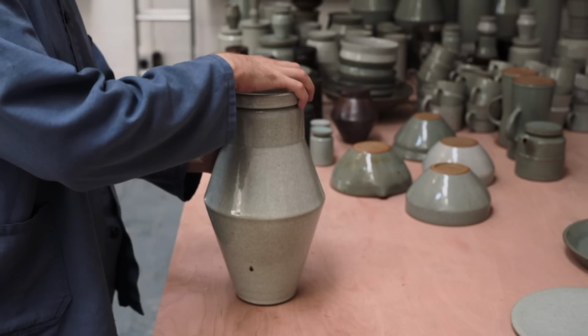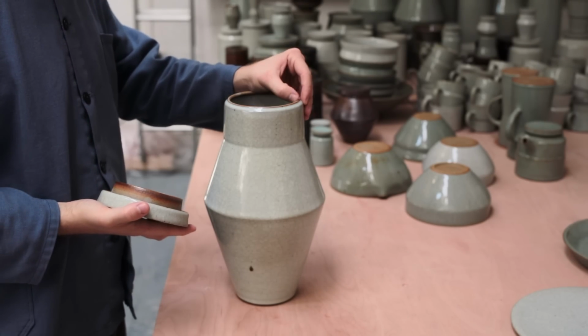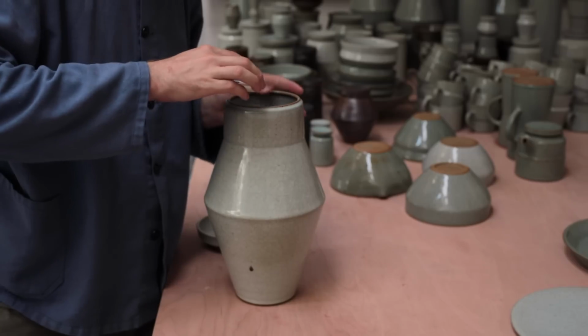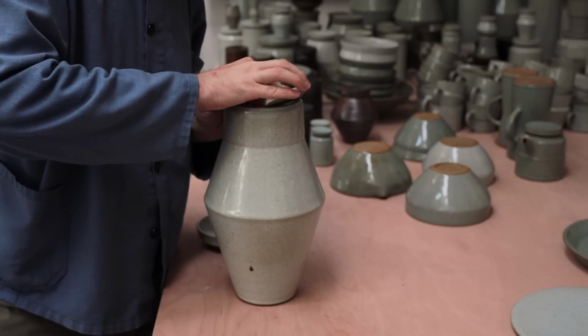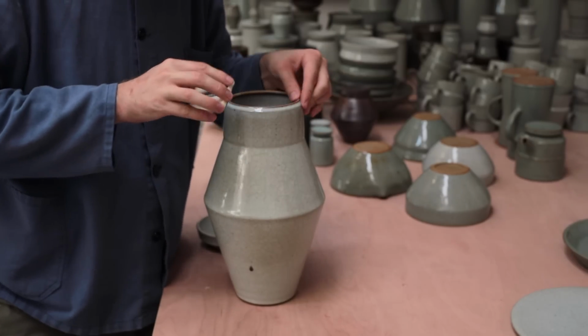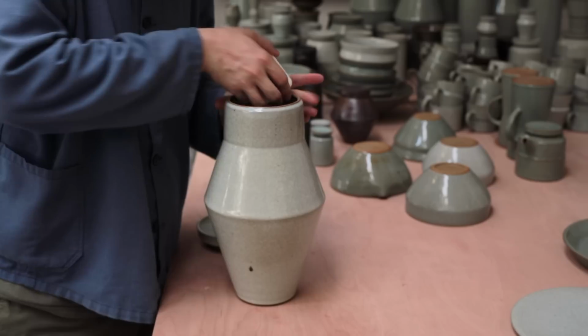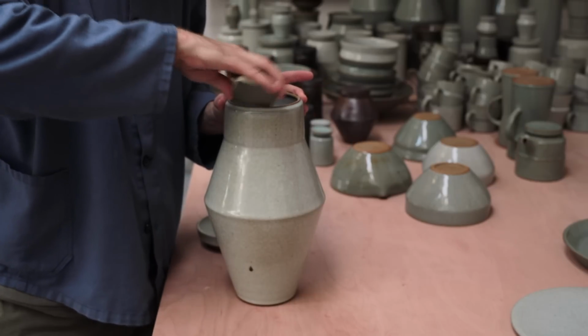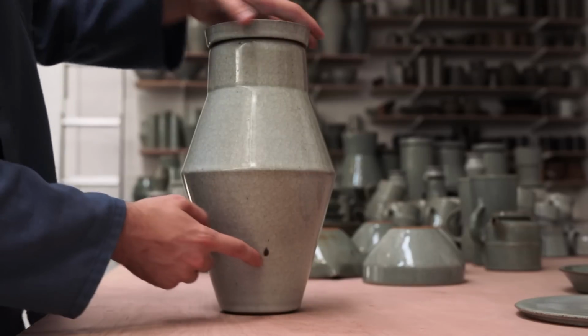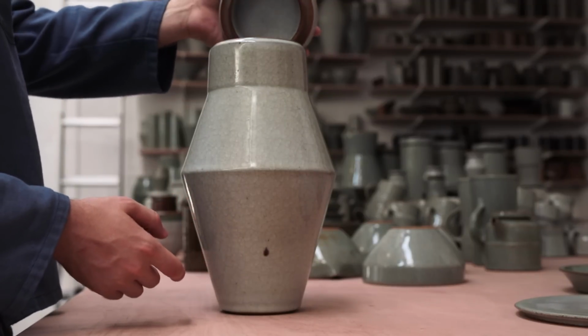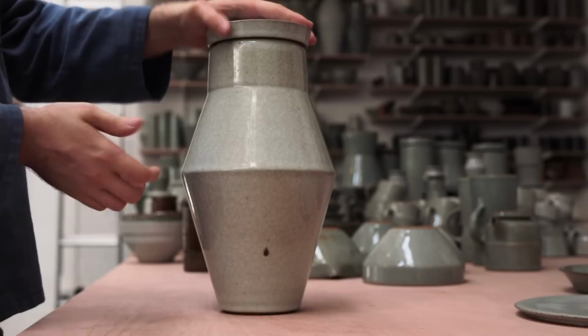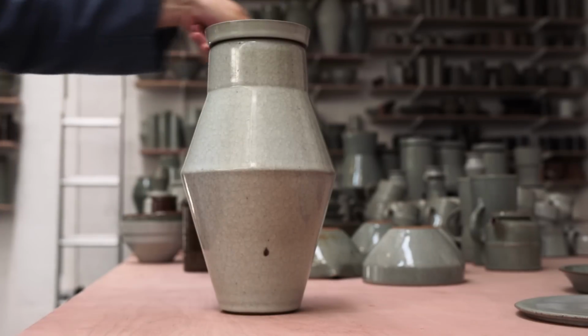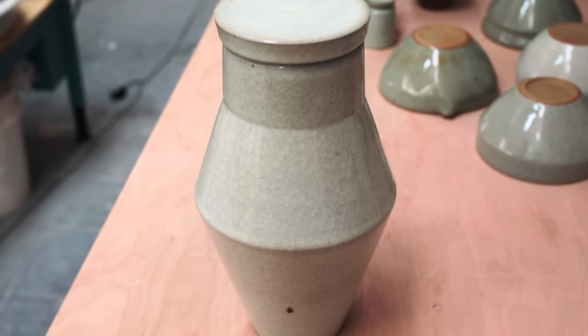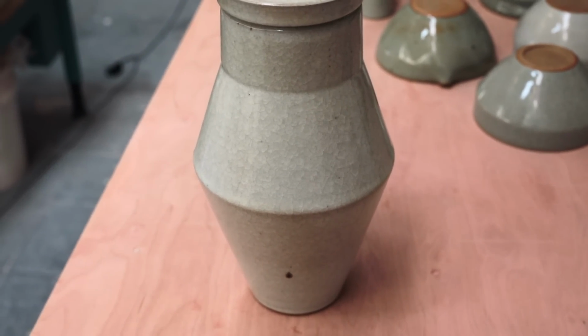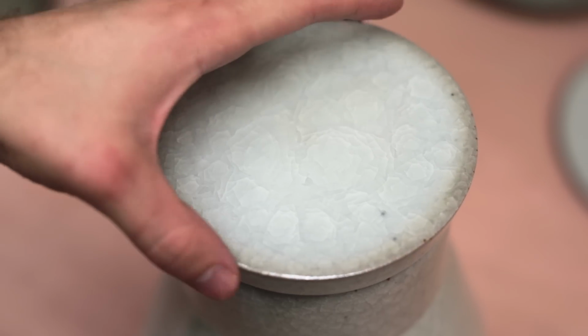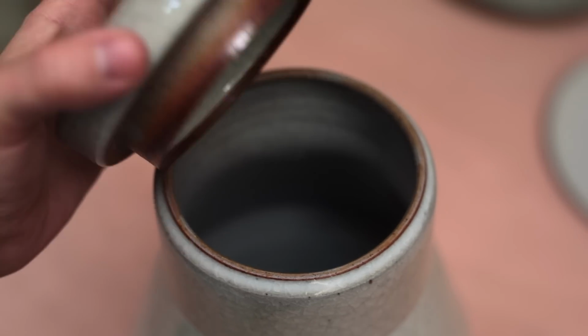And here's the finished jar, although I noticed a few rough patches just underneath the rim where the lapping paste wouldn't have been able to reach. I love this iron blossom on the side, which has appeared completely at random. The glaze itself fired very evenly, and you can see the crackled quality in its surface, especially on the top of the lid where it was applied more thickly.